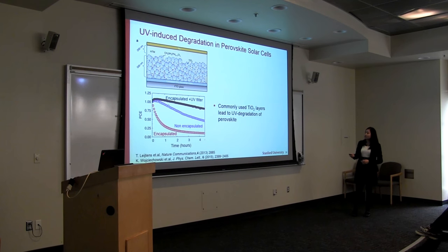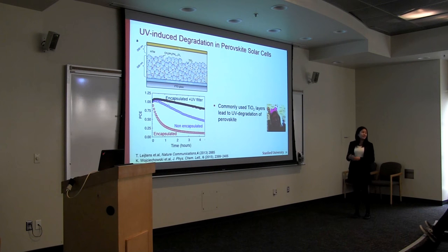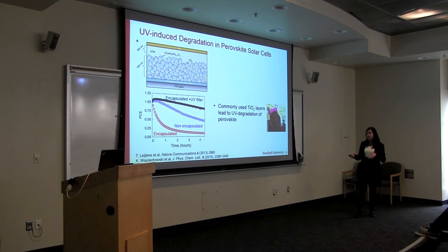This is the common stack of a perovskite solar cell with the titanium, TiO2. People usually use it as a mesoporous nanosphere or as a compact layer. When Thomas shined a UV light onto this solar cell stack, he found that in both encapsulated and non-encapsulated cells, it caused the solar cell to degrade in 4 hours, which is not good. But when he put a UV filter on top of this stack to filter the UV, he saw a very minimal drop in the performance of the solar cell. So this is one promising step to try, but using a UV filter is not desirable.